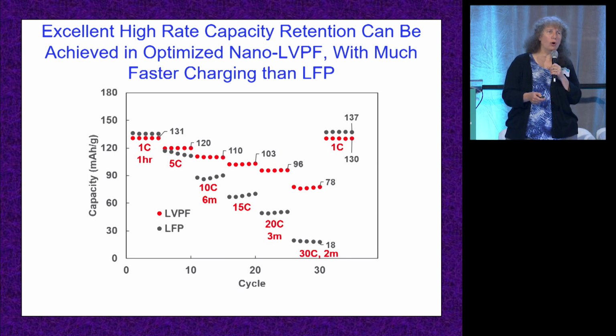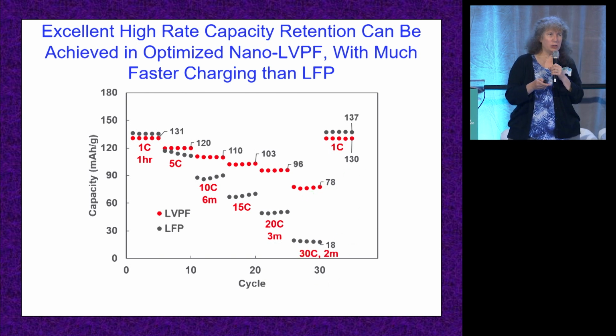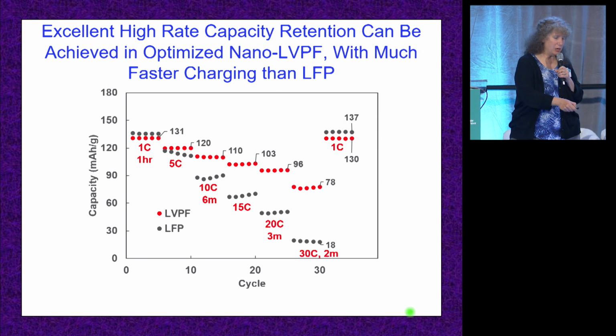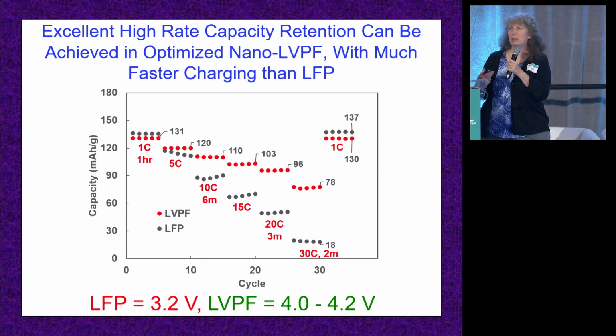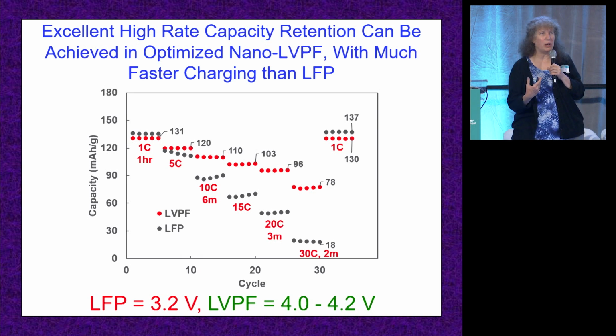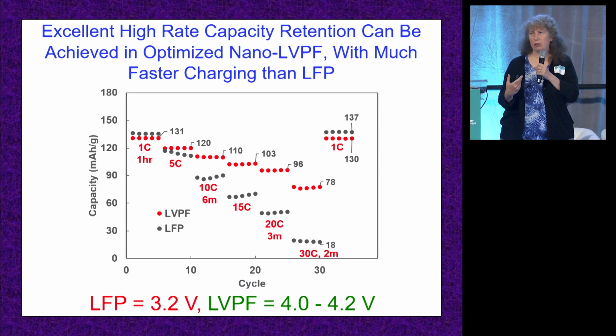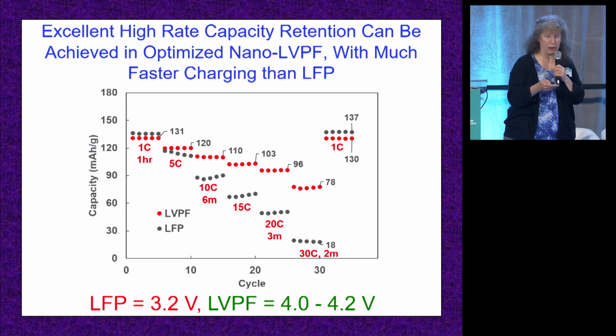This is data for our low-cost, scalable lithium vanadium fluorophosphate in red. I am comparing it to lithium iron phosphate, which is the other low-cost alternative. And what you can see is that the capacity retention of the red material is infinitely better than the lithium iron phosphate. And I also just want to remind you, this is capacity, number of electrons. And that doesn't take into account the fact that the lithium iron phosphate is a 3-volt battery, and our lithium vanadium fluorophosphate is a 4-volt battery.